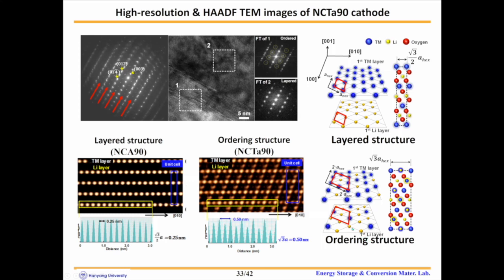ordering structures. We believe that the interchange between lithium and the transition metal is induced by the high-valence tantalum dopant, which changes the charge distribution around itself. This structure seems to enhance structural stability by suppressing interlayer collapse at the highly charged state. And we are further studying these ordering structures.